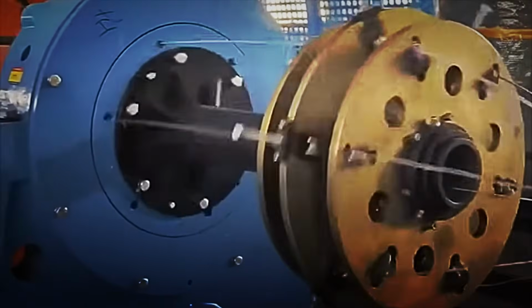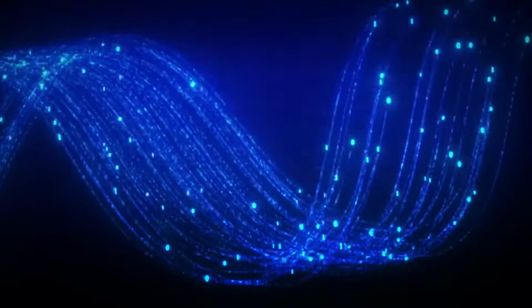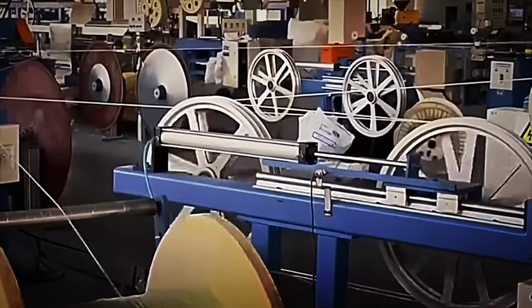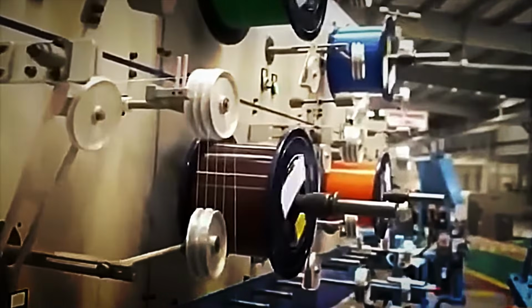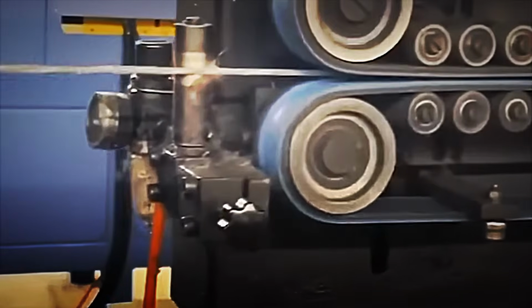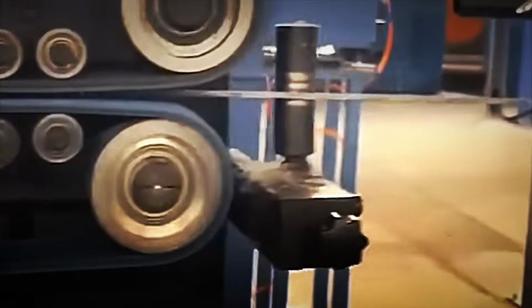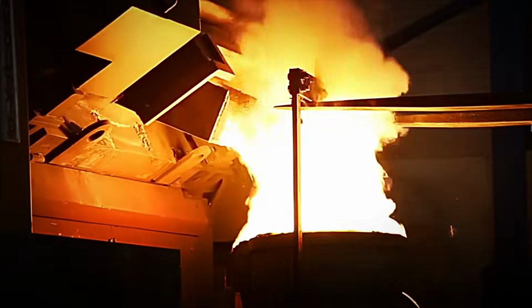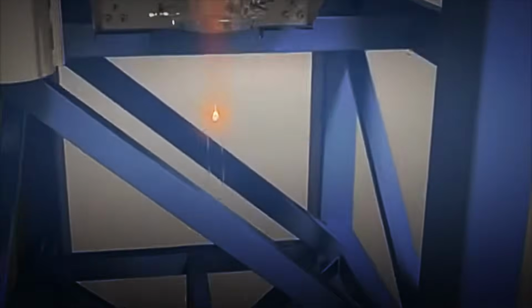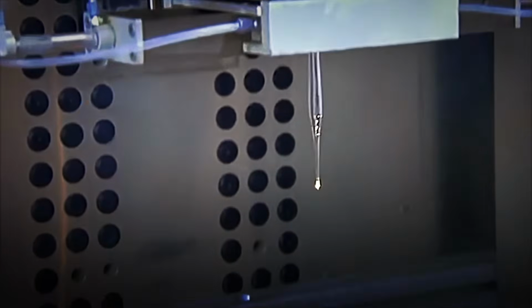The accepted preform is transferred to the drawing tower, a vertical installation that can reach over 10 meters in height. The glass cylinder is placed at the top, while at the bottom a system of bobbins is ready to receive the resulting yarn. The purpose is to transform this solid block into a continuous uniform yarn with a controlled diameter. The lower end of the preform is placed in an electric oven. At this temperature, the glass doesn't break down, but rather softens gradually. The material begins to flow by gravity, forming a droplet, and from this droplet the initial strand of fiber emerges.